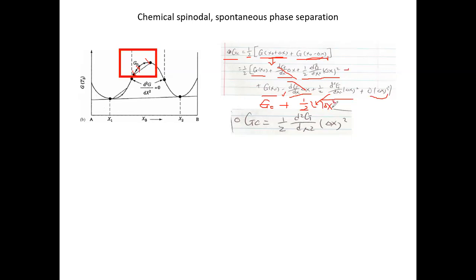This is the free energy after you have the phase state, but with very small fluctuations. And then the free energy difference is that you take this term, the free energy after the separation, minus the original free energy, so that this G naught term is gone, and the only thing left behind is going to be this term. This is going to be the free energy difference before and after.